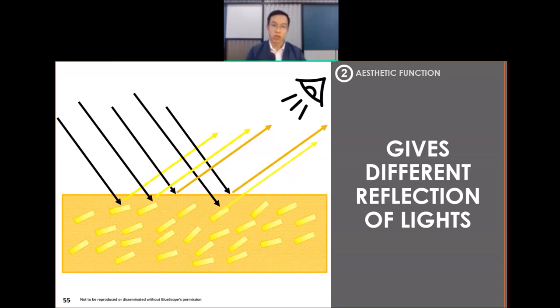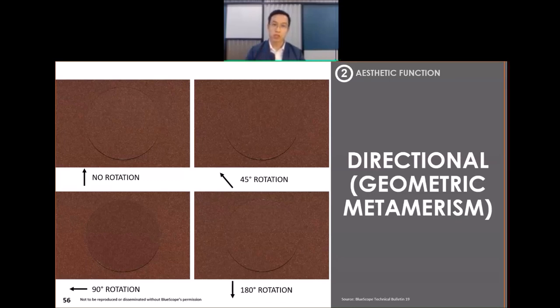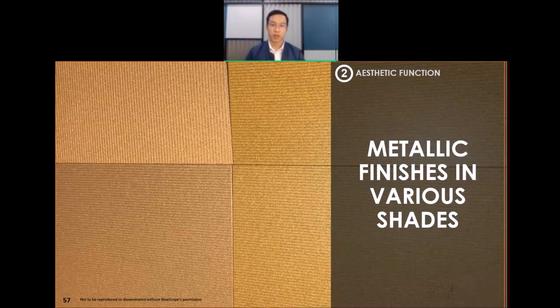If we rotate the panel, most of the reflection will shine onto the mica pigment and you will see more of a glittering effect. That's why metallic finishes exhibit what's called geometric metamerism - if surfaces are oriented in a certain direction and rotated 45, 90, or other degrees relative to each other, they show a different appearance. Here I show examples: no rotation versus 45 degree and 90 degree rotation, where the 90 degree rotation appears noticeably darker.